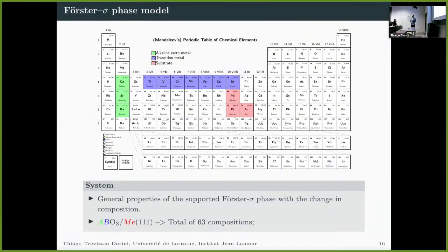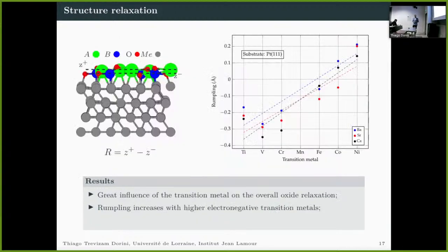I'd like to start with the first part of the results, on analyzing the general properties of the Förster-σ phase model when supported on three different metals and changing the composition of the oxides. Here you can see all the compositions that we have selected. This is green for the alkaline earth elements, all the transition metals, and the substrates. In total, we have calculated 63 compositions.